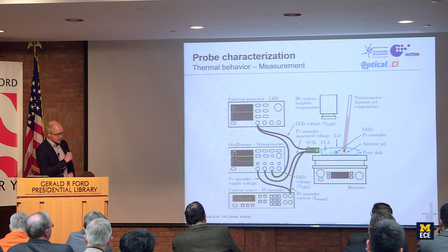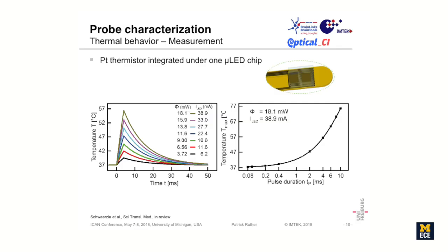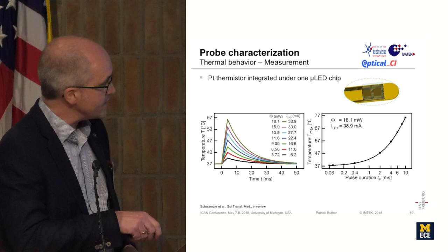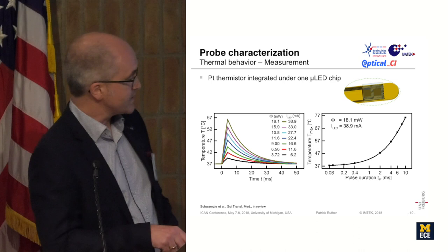In particular, he checks for the temperature of our devices. And what Michael did is he started measuring the heat with the platinum meander under the LED at certain current levels for certain pulse lengths. And what we now see here in that graph is the extraction using a model, predicting the temperature rise and then the decline of the temperature when we use, for instance, in this case, 5 millisecond long pulses at certain current levels.